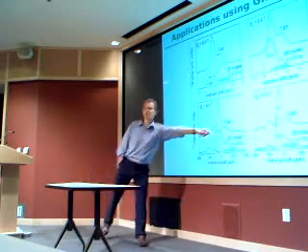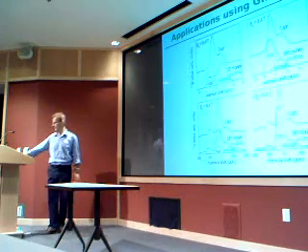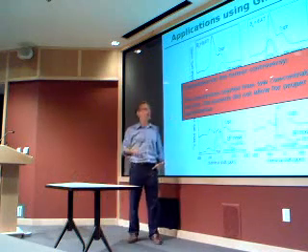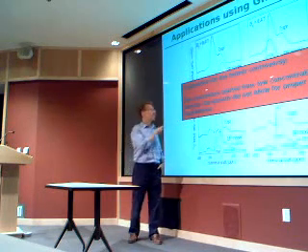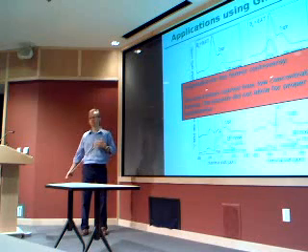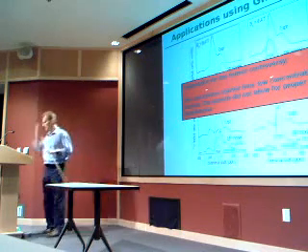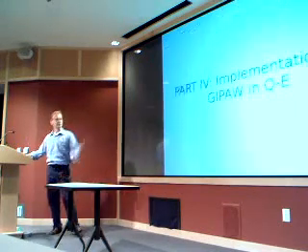So by calculating these experimental observables from electronic structure theory, we can convince ourselves that our model with a high fraction of boroxol rings matches the structure much better than the small fraction. And the explanation was that the simulation started from a low concentration of boroxol rings because the time scale is too short. They don't go to the correct ground state of the vitreous phase. We started from the correct phase, and we showed that it's more stable than what is otherwise obtained from molecular dynamics.